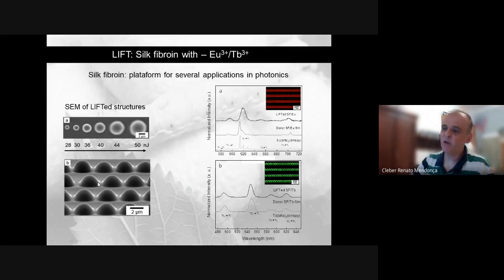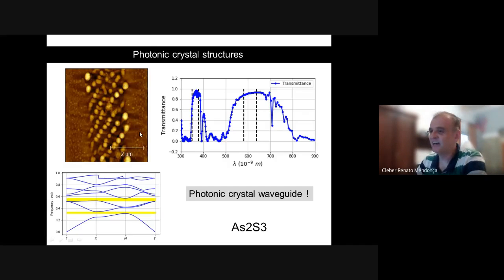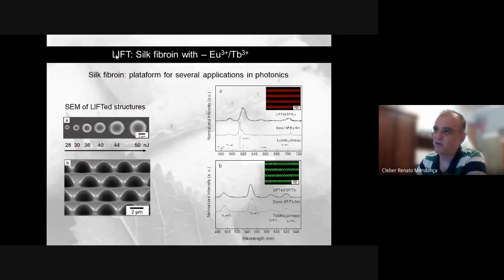So here, what I'm showing are some spheres. As you can see, these spheres are about 2 microns. They are very regular, and they are made from silk fibroin. Silk fibroin is the protein from silk, which is a biopolymer that's being used for several applications in photonics and in biophotonics. In this case, we are transferring this biopolymer using laser-induced forward transfer, LIFT, and those spheres contain rare earths, europium and terbium, so they are luminescent.